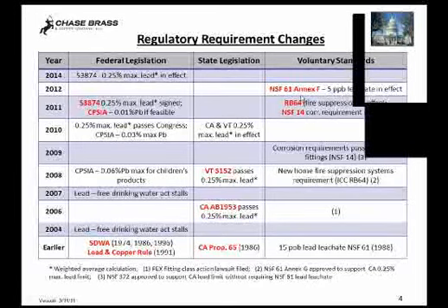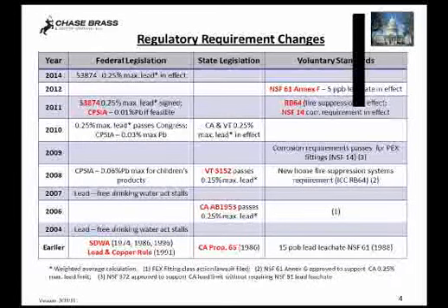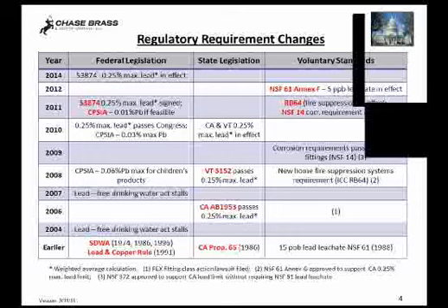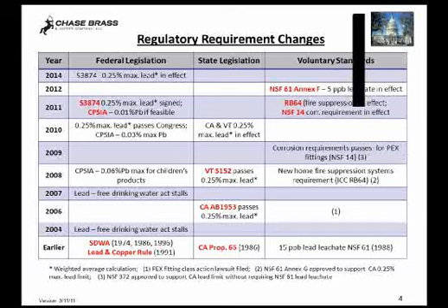In the voluntary standards column, there are three major items to really consider. NSF 61, the Drinking Water System Components Health Effects Standard, set a maximum lead leachate to 5 parts per billion, so significantly tighter because it's not a linear change from 15 parts per billion to 5 parts per billion, but a significantly tighter requirement for lead leachate.